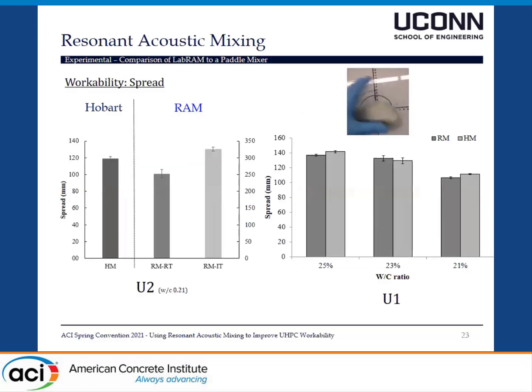And then finally, let's take a look at workability. This time we're just looking at the spread flow test. And here the workability is very comparable to a Hobart mixer. Here it's slightly down when you don't control the temperature of the mixing with a resonant acoustic mixer. But when you control the mixing, the only difference between this one and this one was that the final temperature here was around 39 degrees Celsius, while the final temperature here was roughly 25 degrees Celsius, room temperature. And so we can see that for the most part, it's about the same in terms of workability.